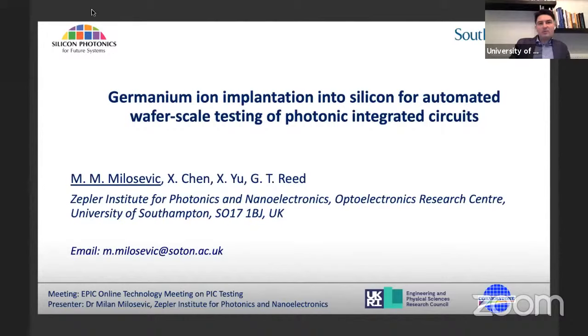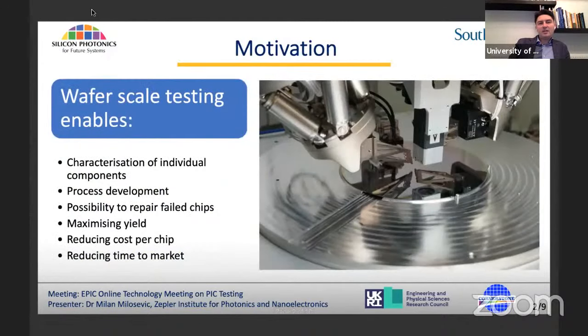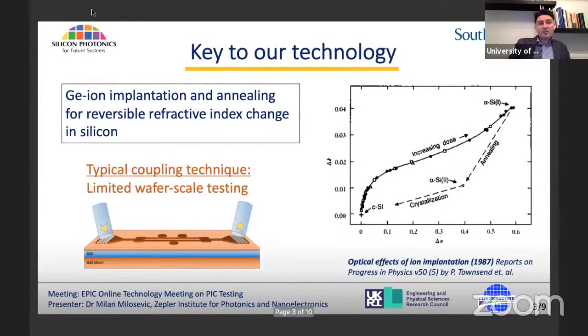So my talk will be about germanium ion implantation into silicon for the wafer scale testing of photonic integrated circuits. As we heard today, there is a whole lot going on in wafer scale testing, and it's definitely a crucial component of any large scale manufacturing line, critical for reducing the cost per chip and for maximizing production yield. Typical coupling techniques for wafer scale testing comprise using grating couplers that can be placed on a wafer in specific positions. However, this gives us limited wafer scale testing capabilities because we cannot test the whole photonic integrated circuit. As you can see in this image, if you want to test this component which is in the middle of the chip, that will not be possible.